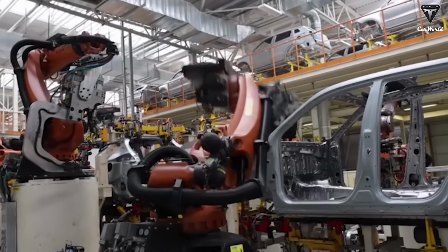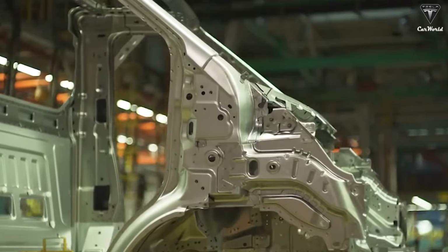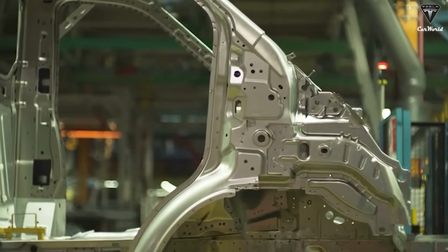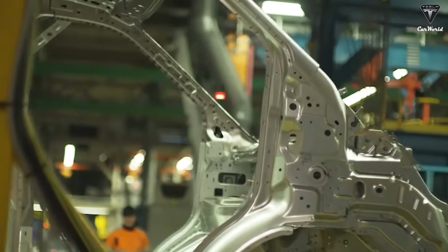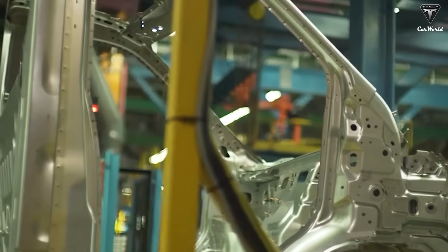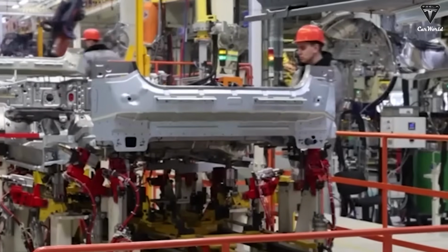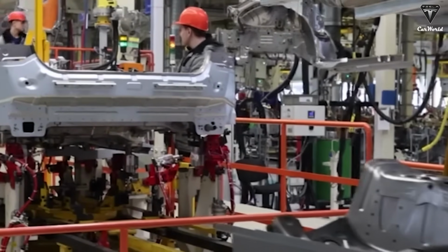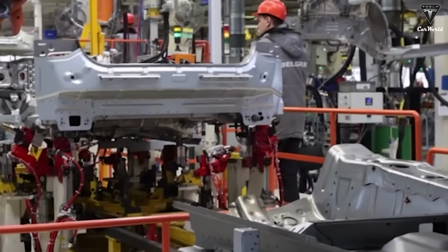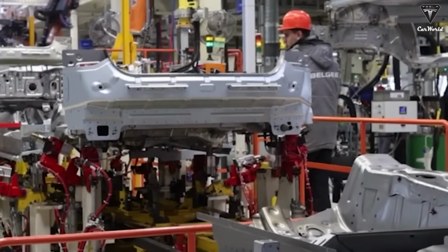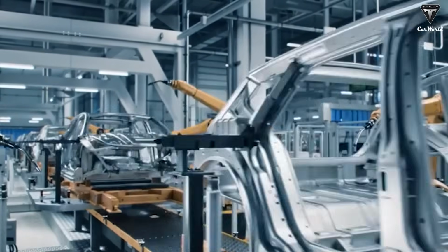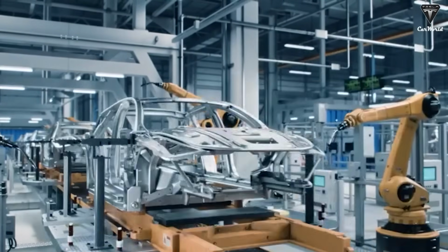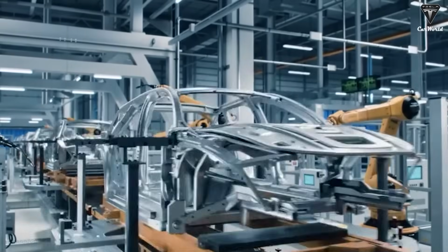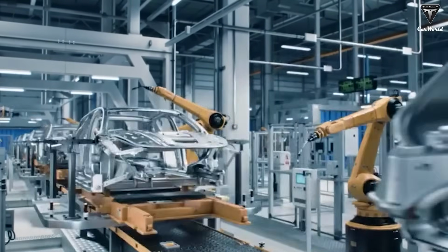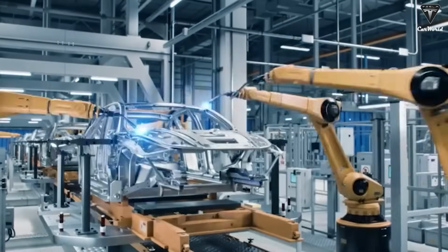After fill, the casting remains clamped while metal solidifies under pressure. Once the solid fraction crosses the release threshold, ejector pins push the part free at roughly 400 degrees Celsius. The still-hot structural casting is immediately transferred to a quench bath, or intensive forced air spray quench cell depending on line setup, to pull temperature down quickly, typically from 400 degrees Celsius to 50 degrees Celsius. Rapid controlled cooling reduces certain shrink porosities, tightens dimensional stability, and sets up the alloy for subsequent heat treat or paint bake tempers.